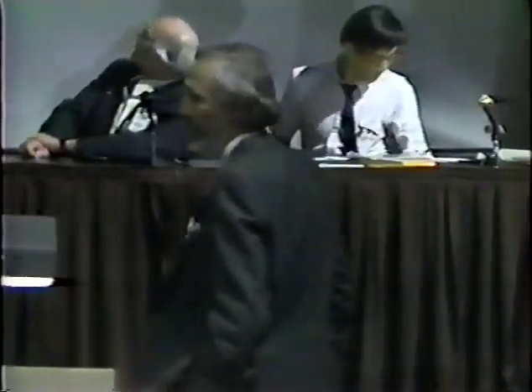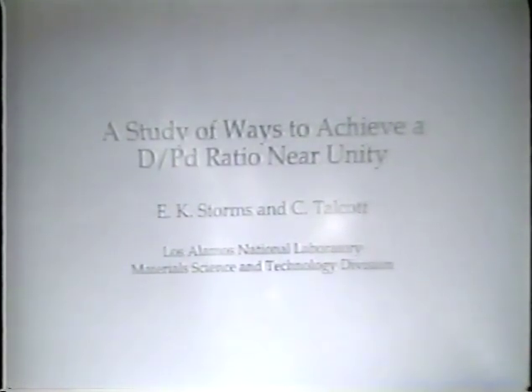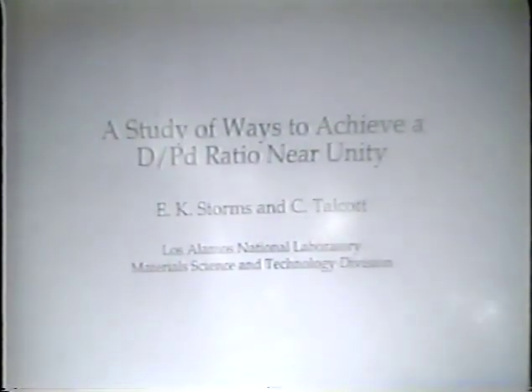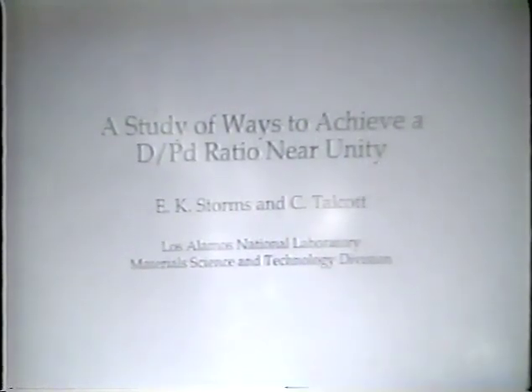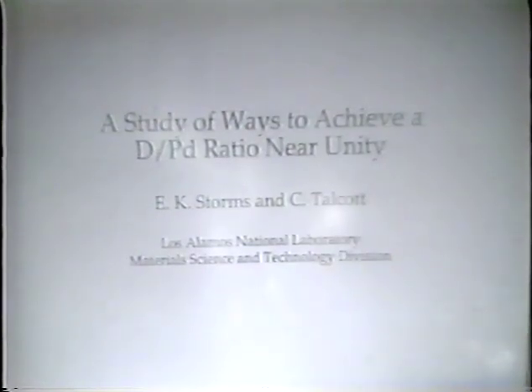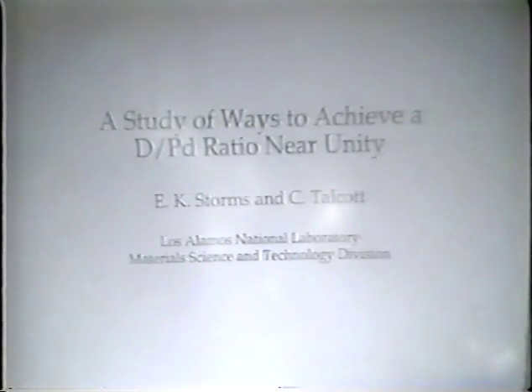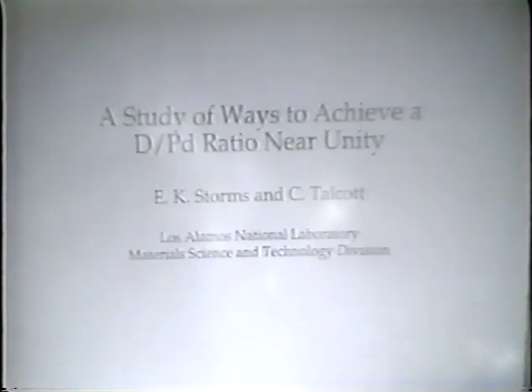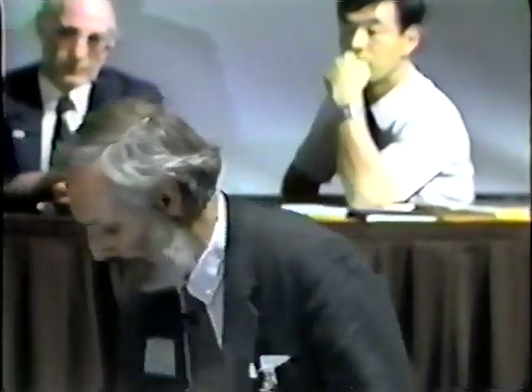Well, I'd like to describe for you a study that Carol Talcott and I have been making in an effort to achieve a very high deuterium to palladium ratio in the electrode. We believe that if fusion is to occur at all, one needs a very high stoichiometry, near or exceeding unity. And indeed, we were treated to some very excellent and well-done studies this morning that showed that PdD 0.8 is probably a lower limit at which fusion does not take place. And if we're going to find fusion, we're going to have to find it in higher stoichiometries. It's a real challenge then to find ways to get to this region.